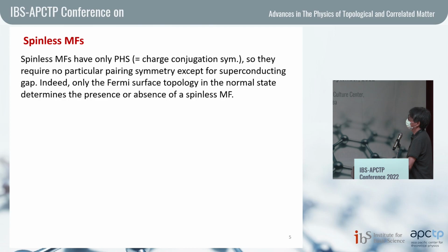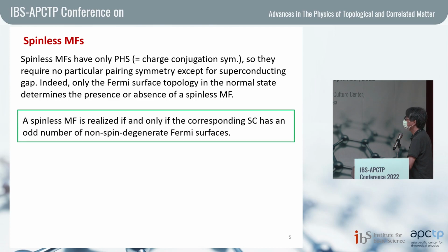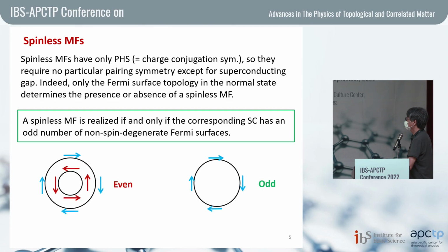Actually, by using the so-called weak pairing assumptions, we can prove the following statement. A spinless Majorana fermion is realized if and only if the corresponding superconductor has an odd number of non-spin degenerate Fermi surfaces. For example, here I consider two different Fermi surfaces. In the left case, I consider spin-split Fermi surfaces like Rashba systems. In this case, we have two non-spin degenerate Fermi surfaces. On the other hand, in the right case, I consider a single non-spin degenerate Fermi surface.